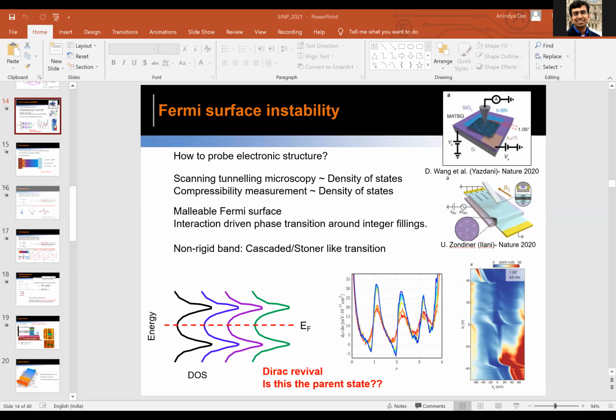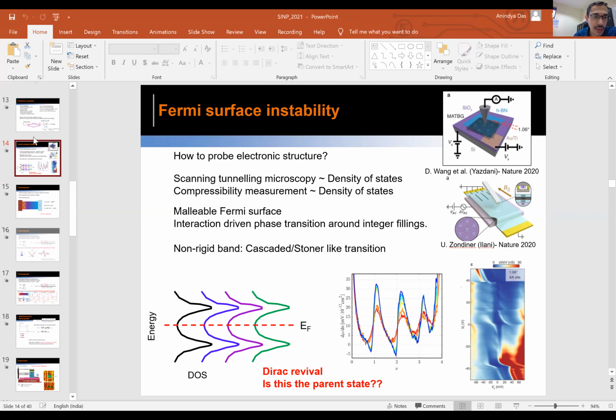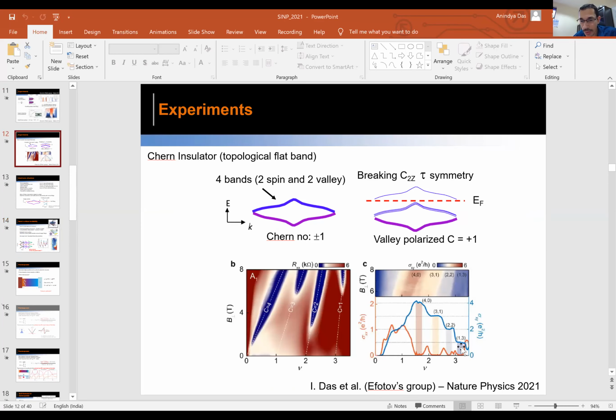Anindya, are these Chern bands? When one of them is occupied, does it have a Hall response? Yes. This sample doesn't show a very nice Hall response, but people have seen it, for example, here. You see my slide? They see quantization. In your experiment, after one Stoner transition, if you had measured, you would have gotten this. We have not, because this was a two-probe measurement, and our device was not clean enough to see some number.